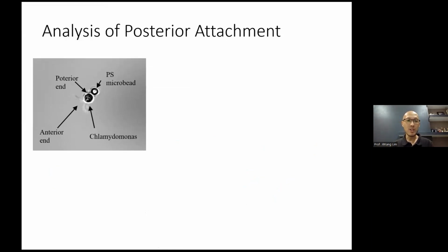So how we did it is, instead of introducing the particles onto the anterior part, at the front part of the cell, we try to attach the beads at the bottom part of the cell. So the presence of this bead is not going to interfere with the movement of the flagella at all. And so if we observe anything, it should be because of the drag alone, because of the geometry change, not because of the obstruction of the flagella.